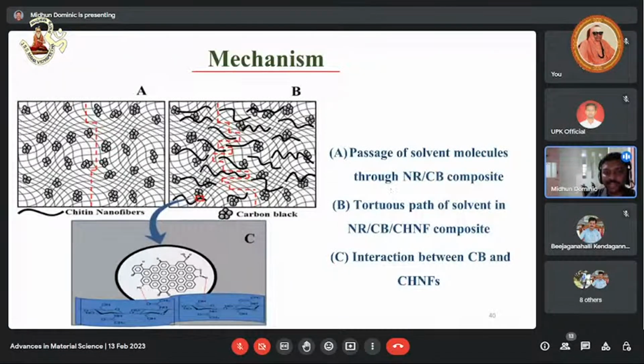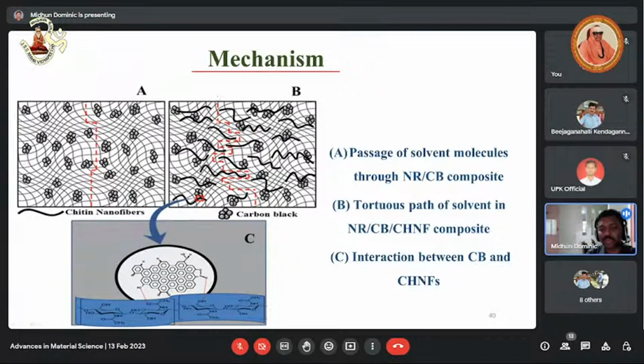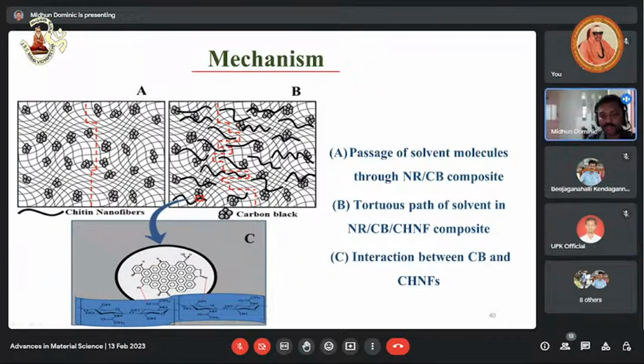This is figure A, which has carbon black alone. The grape-like things represented are the carbon black. And then we have carbon black and chitin nanofiber, where this black color will be chitin nanofiber. In the first example, the solvent molecules can easily penetrate through the sample. But in figure B, these solvent molecules may follow a tortuous path, so more time is needed. That is why swelling index decreases.